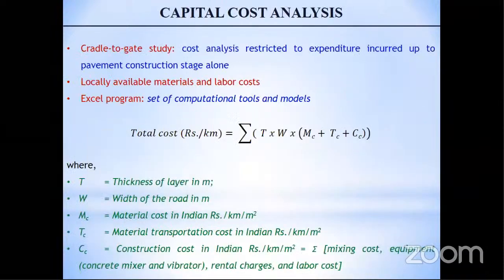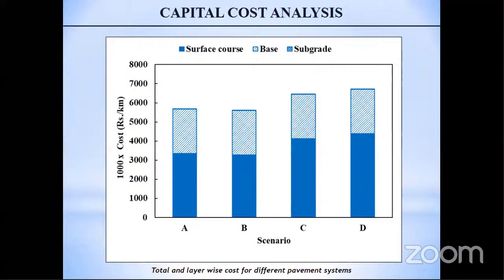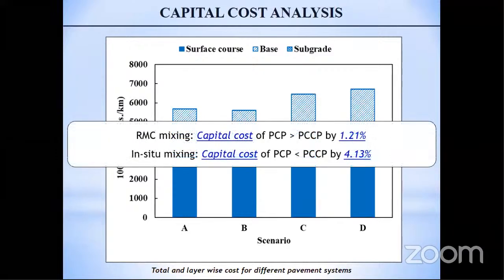Now, once the environmental benefits were quantified, the cost analysis was performed using the model which is shown on the screen right now. Again, it was observed that for RMC mixing, the cost of pervious concrete construction was higher than that of Portland cement concrete by about 1.2%. Whereas for in situ mixing, the capital cost was lower by about 4%.